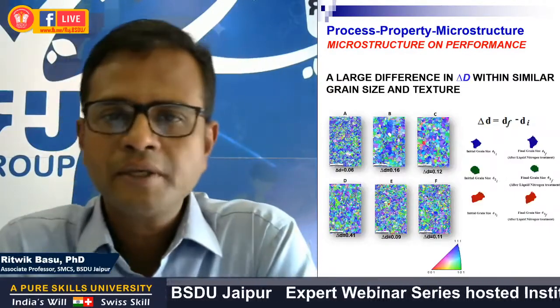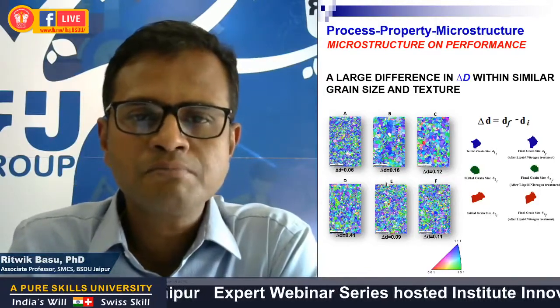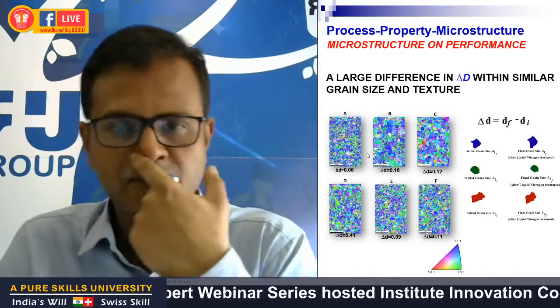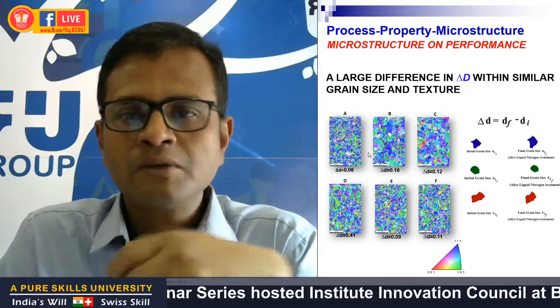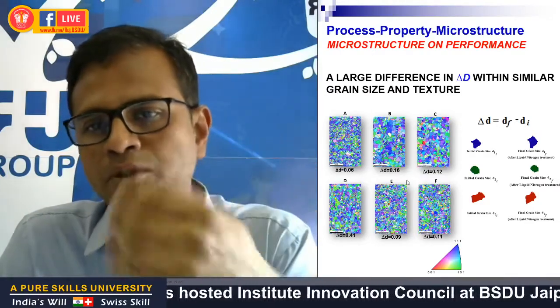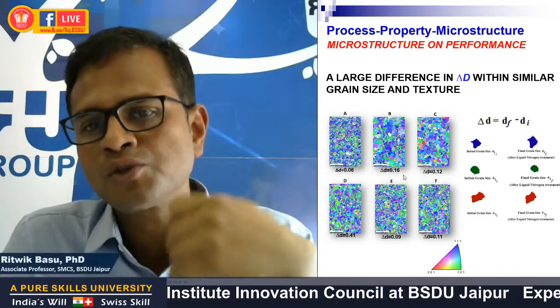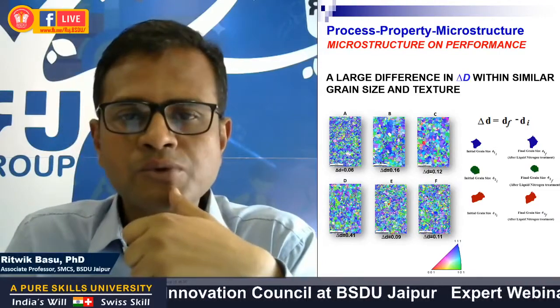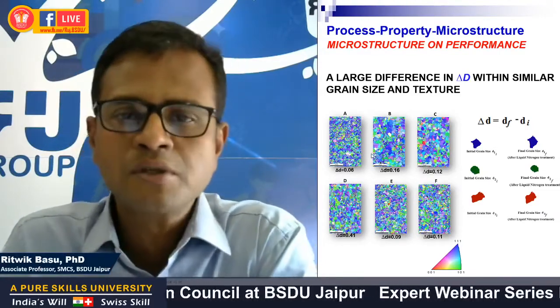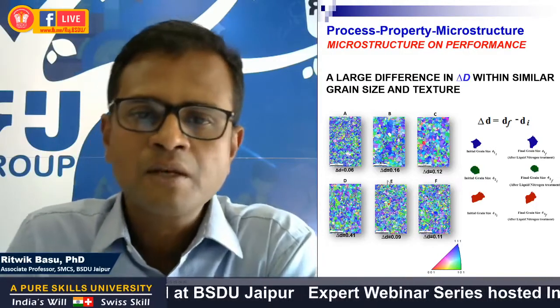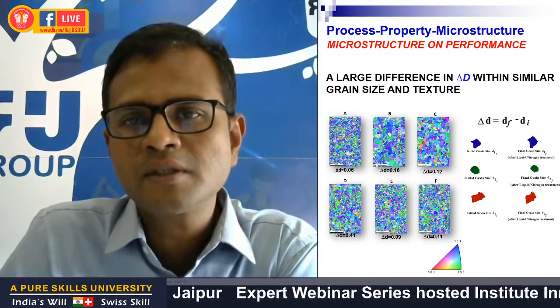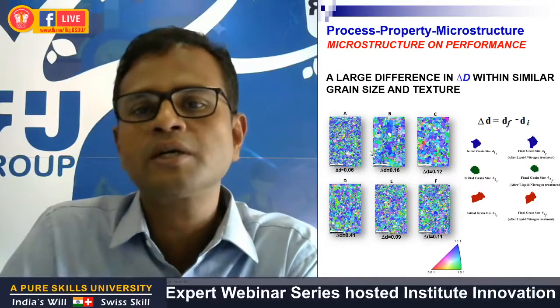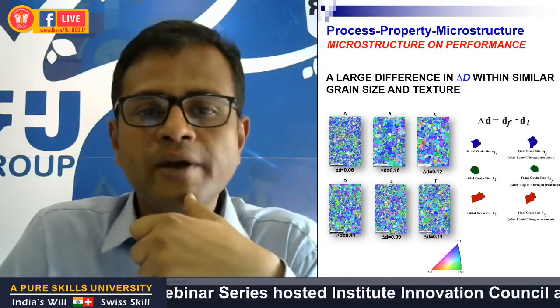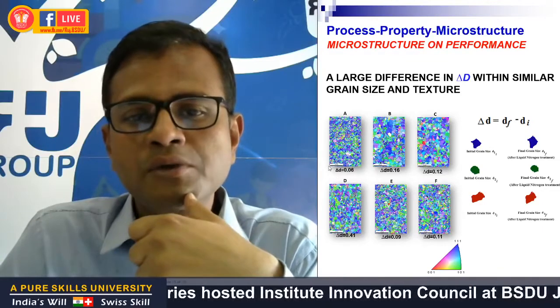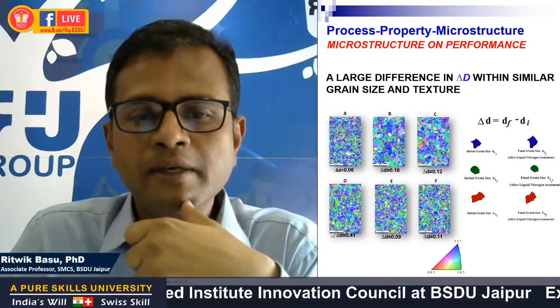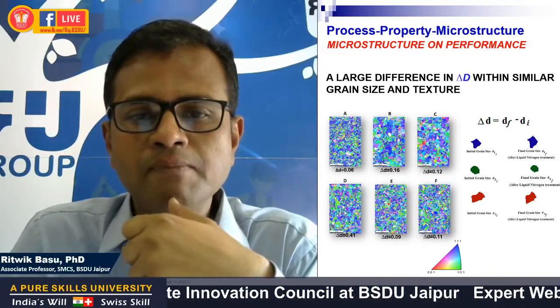So we actually generated a few different microstructures through the marforming route, followed by intermediate and final annealing treatments. We then subjected each of these samples to one thermal cycle. What we could see is that the microstructures, though different, have textures that are not significantly different. But what is more importantly different is the irreversible strain, or what I call the non-recoverable strain, which varies from the lowest of 0.06 in sample A to the highest of 0.41 in sample D.